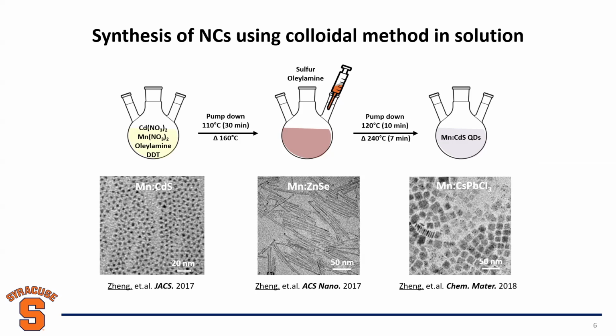It turned out that the structure of the host lattice is a key parameter to tune the final morphology. In this case, cadmium sulfide is a cubic phase: a, b, c equal, with 90 degrees between the three axes. Right? You don't have structural anisotropy. You make cubic phase spherical quantum dots. And here, this one has a host lattice in the wurtzite phase, or hexagonal phase. They have a longer c-axis. You have structural anisotropy at the atomic scale. So that dictates the growth behavior of your nanocrystals.